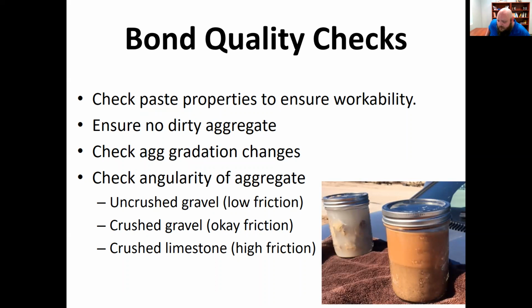I put halfway full of rock, halfway full of sand on each of these jars, and I filled up the rest of the way on both jars with water. So one jar just has coarse aggregate and one jar just has fine aggregate. I shook them up with water and let them set for an hour, and that's what they look like. It was very clear, holy smokes, that sand, half of it's clay. Well, that really messes up not only air, but it messes up strengths and bonds and everything else. So you've got to be really careful.